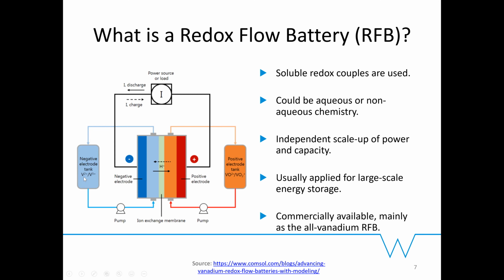So when you want to have energy transfer, either charging or discharging, you pump the electrolytes into the power converting module, which is where the electrodes and the membranes are, or the membrane electrode assembly. And you can have charge transport, and you can also have controlled migration of protons or sometimes sodium ions, depending on if you're using an alkaline system. Then you have to change the migration of the particular species here. It's via the membrane, because of this unique ability of storing energy in soluble components like all vanadium.